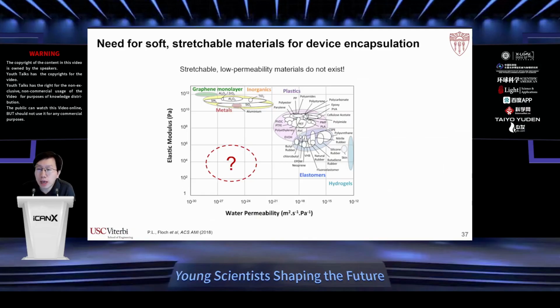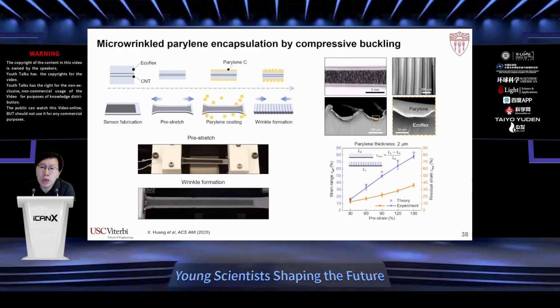Because if we want to have soft, stretchable, implantable devices to operate for long term in biofluids, we have to find an encapsulation layer that's able to stretch and also prevent fluid, mostly water, permeation. So the strategy we chose was to use an existing, well-established biocompatible material, which is parylene C, which has pretty good barrier property to prevent water penetration. But parylene C is not intrinsically stretchable.